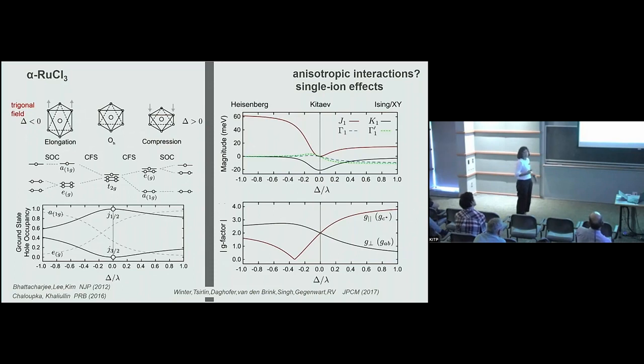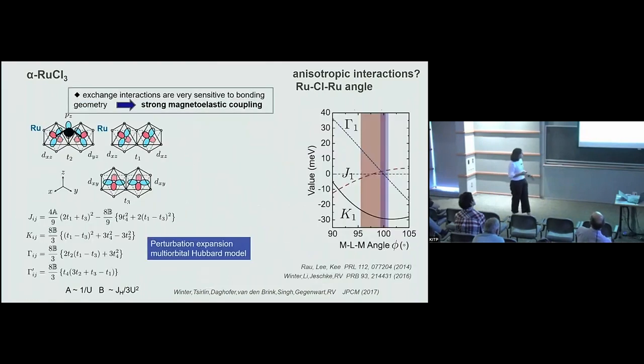And of course, the g-factor will also be anisotropic. So this already is telling us that we are going to expect, apart from Kitaev interactions, other interactions due to the fact that we have this single ion anisotropy. And not only that, what we have in the material is that these octahedra are coupled, and therefore there are going to be different types of hybridizations depending on what type of ligand atoms we have in between these transition metal ions.